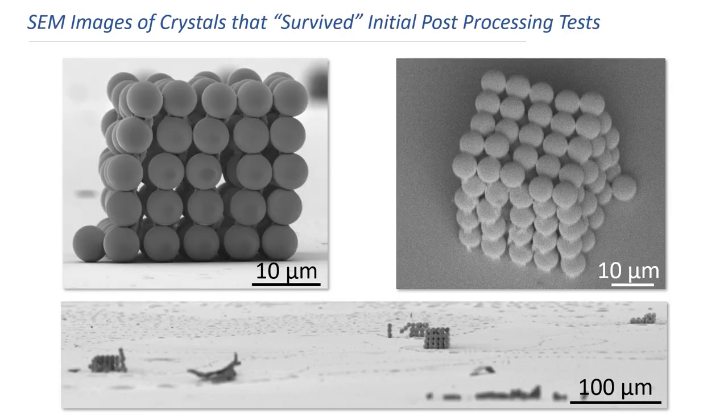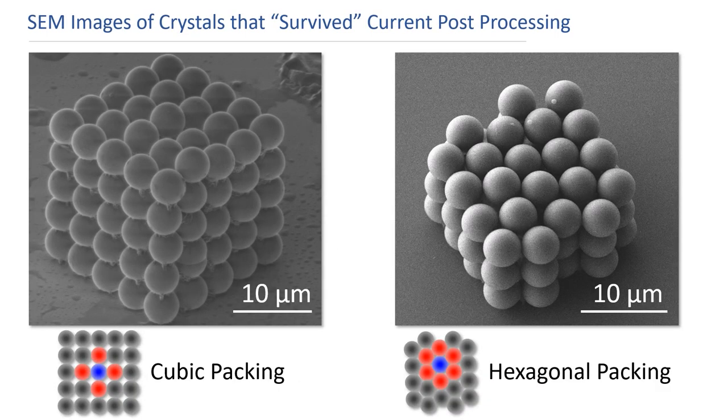Once the microgranular crystals are fabricated in our microchannel, post-processing them so that they are safely exposed to air for testing purposes is not a trivial issue. When we first fabricated the crystals we tried to directly flush the photocurable polymer out of the microchannel using air and we learned that surface tension tidal waves warp and destroy the crystals architecture as shown here. These SEM images better show how the crystals were warped and deformed by tidal waves of surface tension. These crystals are much cleaner since we first flushed their channels out using ethanol and then exposed them to the air. Our lab now has a critical point dryer and we are excited to see how much that machine improves our post-processing results in the future.